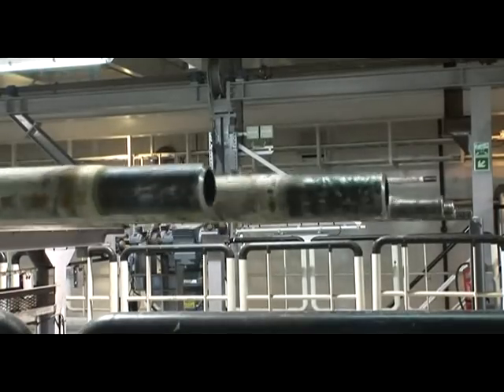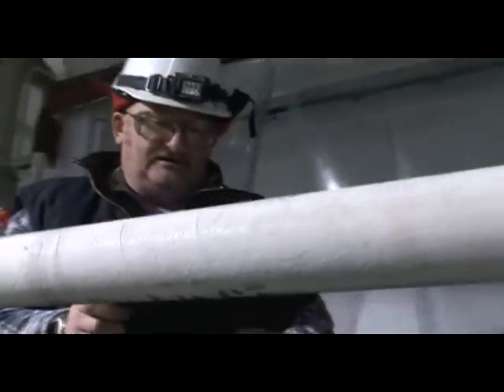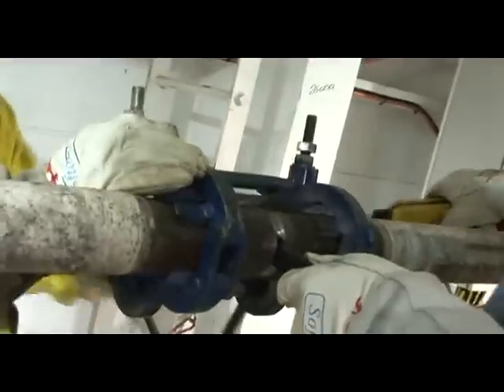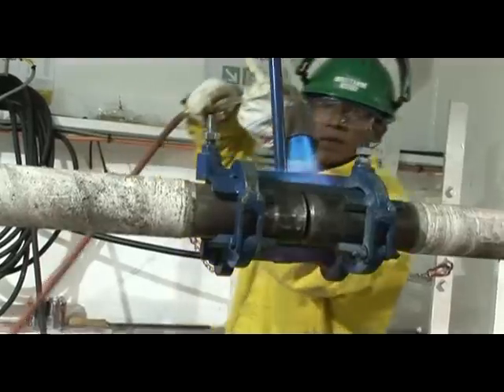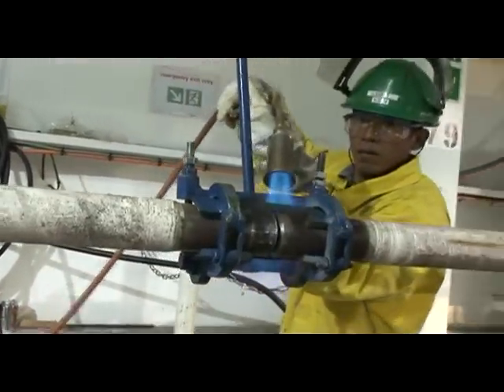Parallel to the production of the 16-inch pipeline in the main firing line, the 2 2-inch chemical injection pipelines go through similar stages in the piggyback firing line. Next, the pipes are finished and lined up with an external line-up clamp. The pipe then gets preheated. The piggyback bead weld is done using TIG welding.